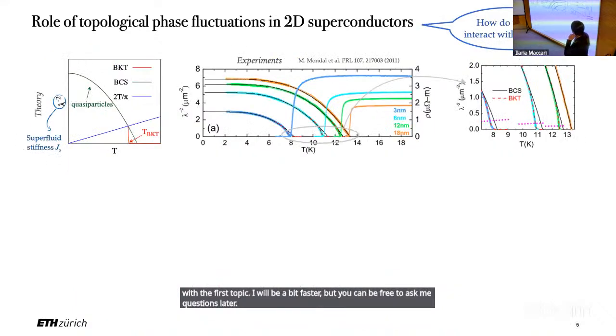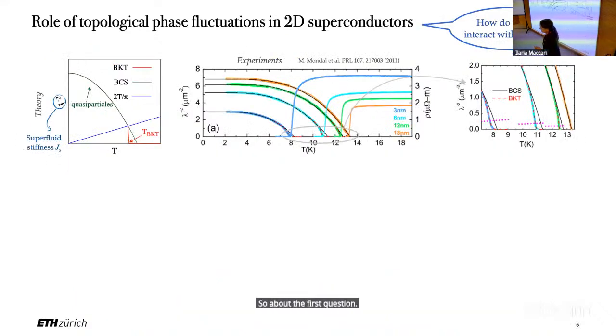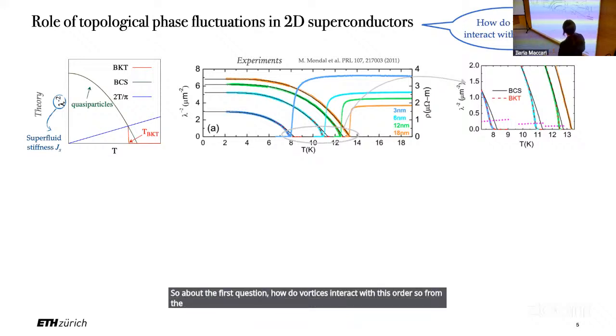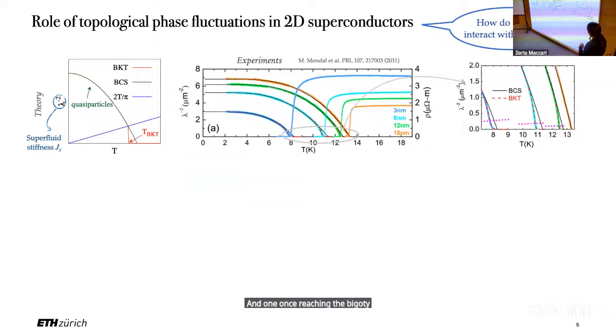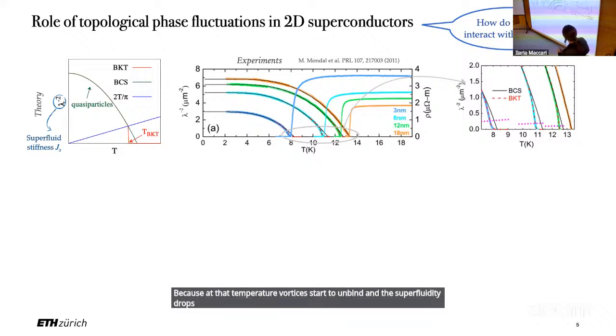So about the first question, how do vortices interact with disorder? From the textbook picture, we know what we should expect in a thin superconducting film. The superfluid stiffness should follow in temperature a BCS-like trend due to the unbinding of quasi-particles. And once reaching the BKT critical line, one should observe a jump, because at that temperature, vortices start to unbind and the superfluidity drops suddenly to zero.